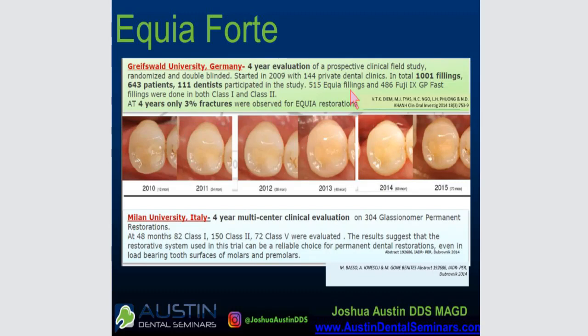And when I was in dental school, it was kind of verboten. It was almost like you were locked away in the brig, and the key was thrown away if you suggested even thinking about putting a glass ionomer on a class 1 or class 2 lesion. And if you look at this study that was done in Greifswald, Germany, a 4-year evaluation, 1,000 fillings were done with this Equia Forte, class 1s and class 2 situations. At a 4-year recall, only 3% of Equia Forte restorations done in class 1 and class 2 situations had fractured. So this is a pretty big study that shows that at 4 years, 5 years, somewhere in there, you can use a material like Equia Forte in the right scenario in a class 1 and class 2 situation.